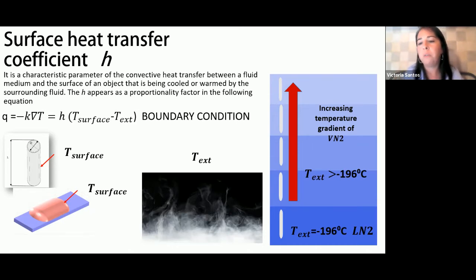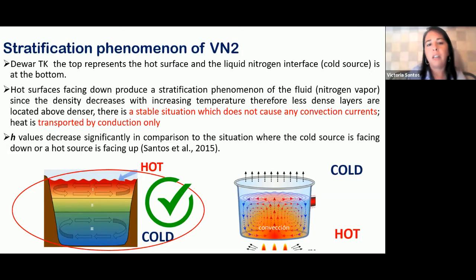And that, as you know, we have liquid nitrogen at -196, and as we move in a vertical direction, we have an increasing temperature gradient of nitrogen vapors. What we have in a Dewar tank is a stratification phenomenon of the nitrogen vapors. The top of the Dewar represents the hot surface, and the liquid nitrogen would be the cold source. So when you have a hot surface facing down, you have a stratification phenomenon because the density decreases with increasing temperature. So the less dense layers are above the more denser ones, and therefore there is no convection, and the heat is transported by conduction only. This fact means that the H decreases in value in comparison to the opposite, for example, for a heated pot where the cold source is facing up.